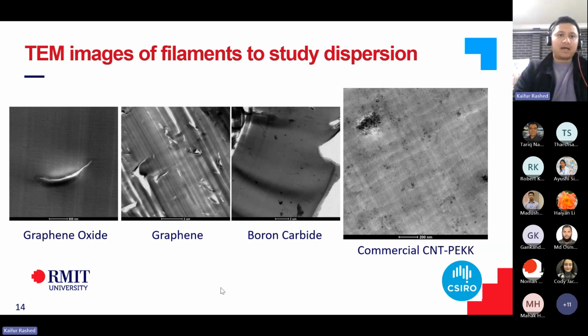So I performed TEM on the filaments as well. I took a cross section and then analyzed them under TEM to study the dispersion and distribution of the additives within the polymer matrix. So graphene oxide shows good signs of intercalation, and so does graphene. But boron carbide, we could only get fragments, because boron carbide was very hard, even though we used a diamond tip to slice the samples, we couldn't get complete cross sections on the boron carbide reinforced PEKK because of its hardness.